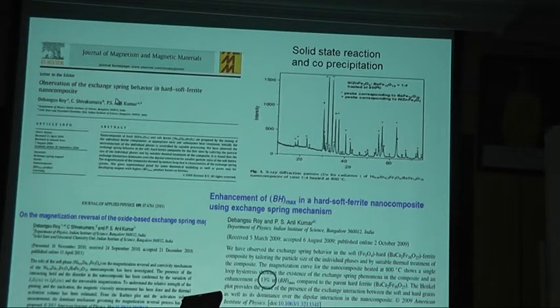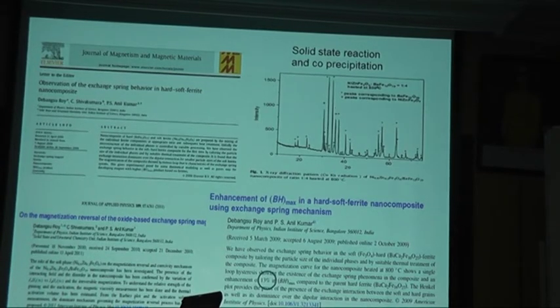The first paper was in 2009, and then this one in 2009, 2011, and this one around 2009. Surprisingly, he only used solid state reaction. I read the paper. He also combined barium ferrite and nickel zinc, but they prepared nickel zinc by a soft chemical method, precipitation. For barium ferrite, they prepared it using solid state reaction, which means just the conventional method.